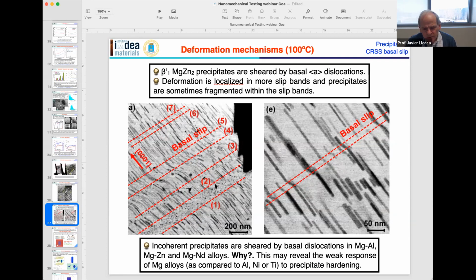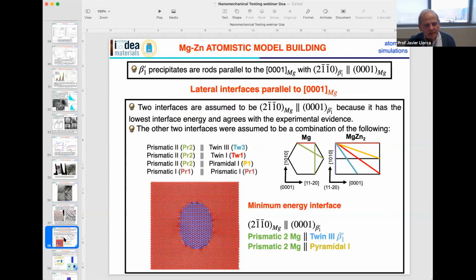So we just really wanted to know what were the mechanisms that were responsible for that. And in order to do that, we did some simulations. So basically what we did is we do a molecular dynamic simulation. This is the precipitate, this is the basal plane, and we use a molecular dynamic simulation where the precipitates are long rods that are perpendicular to the basal plane.